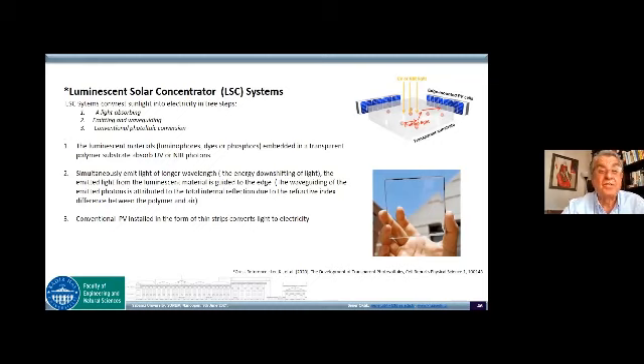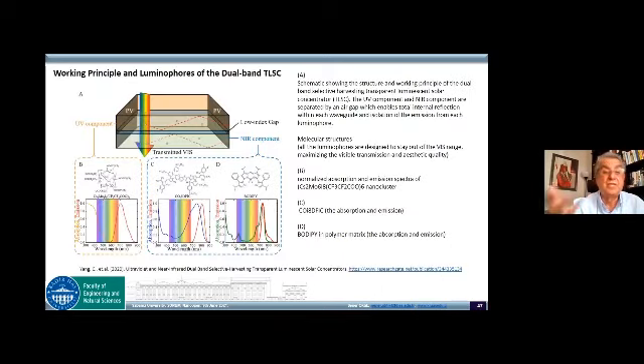An LSC system is light absorbing, emitting and waveguiding, followed by conventional photovoltaic conversion. So in LSCs, you use conventional photovoltaics at the edge. What you really do is direct all the energy, probably changing the wavelength, to the side to convert it to electricity. So you use luminescent material, luminophores, dyes or phosphors, embedded in a transparent polymer on the surface. This absorbs UV and near infrared, and through the waveguide, you send it to the edge of the windows. This is how it works.